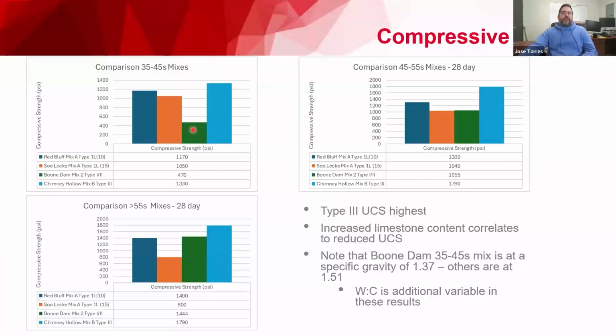This one mix here in the 35 to 45 seconds is actually outside of that 1-to-1 ratio I was talking about. This is probably why this is so low. Your cement content will do a lot for strength, and we're trying to compare apples to apples as best as we can. But generally keep in mind that how much cement you have in there will change your strength and your set times.